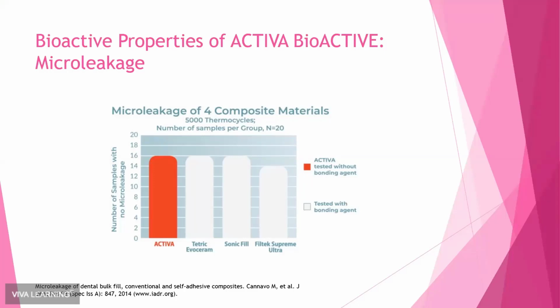So what we're looking at here is, after 5,000 thermocycles, the number of samples that had some sort of microleakage. What's really interesting about this is that the composites were all tested with a bonding agent, but the Activa was tested without a bonding agent. It was just put into the tooth after being etched. So it is performing exactly the same, if not slightly better than standard composites on the market without even bonding, because of its ability to form the apatite formation and the mineral tags that are going into the tooth.